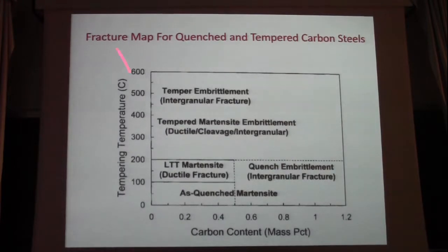Now, here's a map I created. This is a map of tempering temperature. One thing, we make martensite by quenching, but then we control the mechanical properties of the martensite by tempering. Most of the time, hopefully, we're okay, but here's where these intergranular mechanisms can develop. Quench embrittlement happens here. We temper it between 100 and 200. It's okay in low carbon steels, but not in a high carbon steel. When the carbon content goes above 0.5%, then you get quench embrittlement, you get this intergranular fracture.